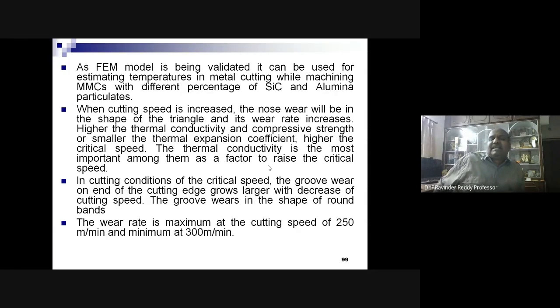When cutting speed is increased, the nose wear takes the shape of a triangle and its wear rate increases. The higher the thermal conductivity and compressive strength, or the smaller the thermal expansion coefficient, the higher the critical speed. Thermal conductivity is the most important among them as a factor in raising the critical speed. In cutting conditions at the critical speed, the groove wear on the end of the cutting edge grows larger with the decrease of cutting speed. The groove wears in the shape of rounds or bands. The wear rate is maximum at the cutting speed of 250 meters per minute and minimum at 300 meters per minute.